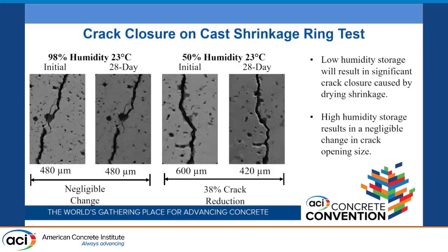After that, we looked at the crack closure problem. Are these cracks just going to close after we remove them from the test setup? We did notice previously that when we left one on too long, a second crack would form, just because it's starting to re-tighten on itself.